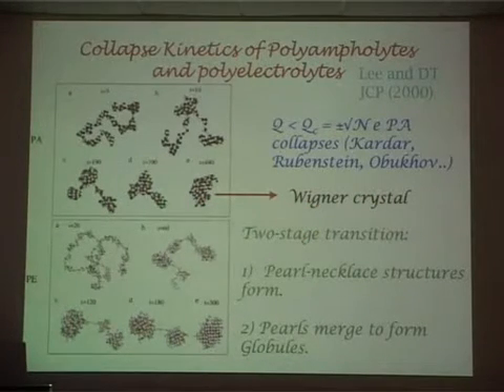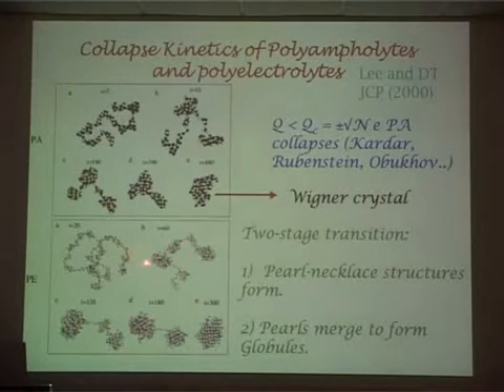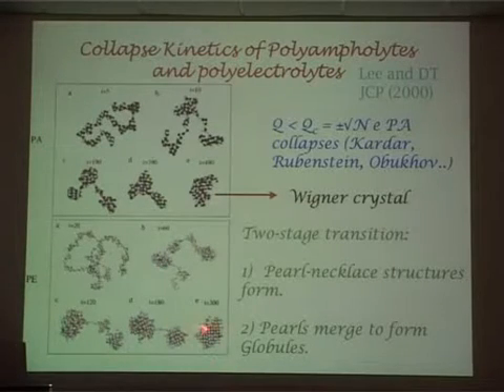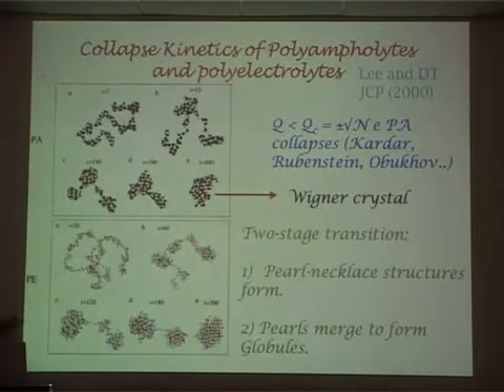You can look at the same sort of thing for a polyelectrolyte. This is a polyelectrolyte with some attractive interaction, and it undergoes a coil globule transition. You can see from both of these that you form some clusters in the beginning, and then the small clusters start to grow, and once you form a large cluster, it starts to swallow up the small clusters until you get one final cluster. The mechanism is basically the same in both cases. Here, of course, you have some kind of order very similar to this; both are small pieces of Wigner crystal.